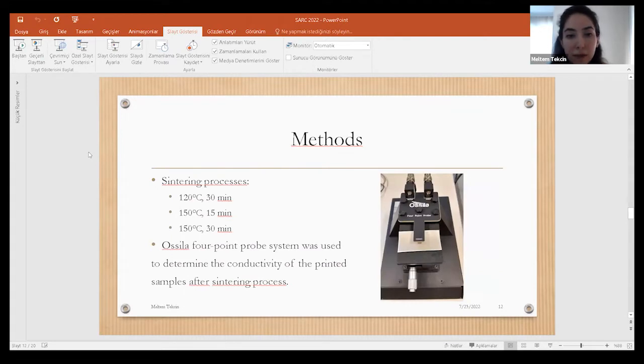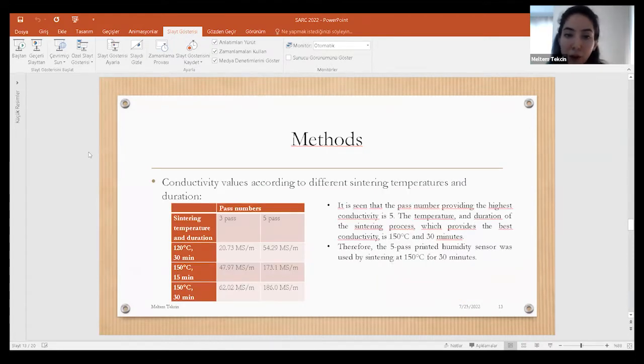After the printing process, we applied sintering processes. We applied different sintering processes, such as 120 degrees for 30 minutes, 150 degrees for 15 minutes, and 150 degrees for 30 minutes. An Ossila four-point probe system was used to determine the conductivity of the printed samples after the sintering process. Conductivity values according to different sintering temperatures and durations are given on this table.